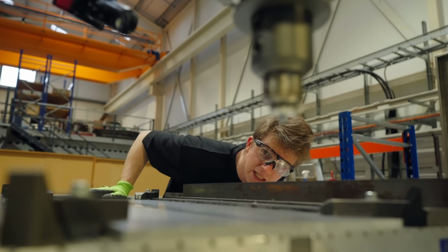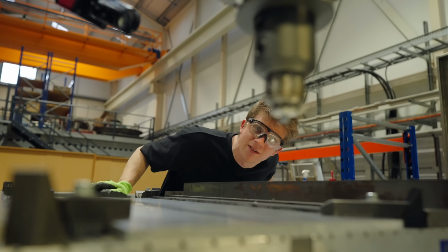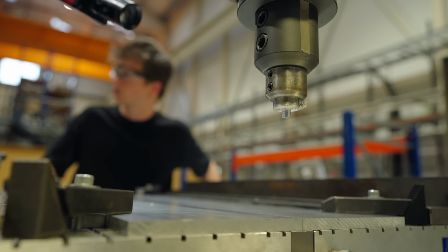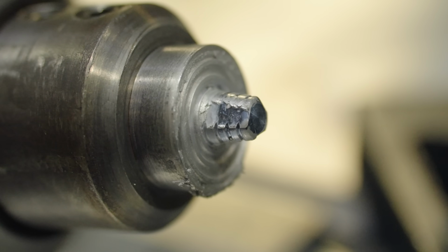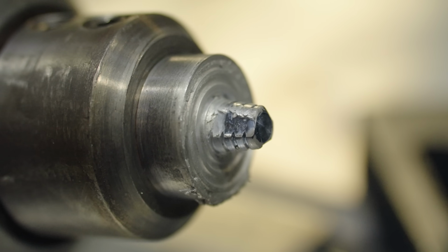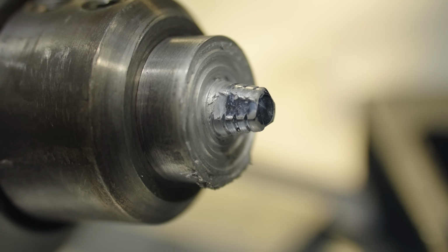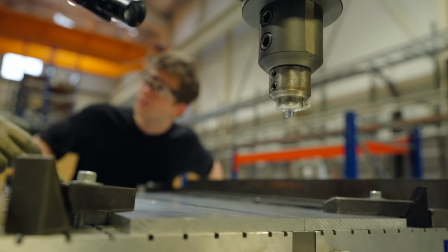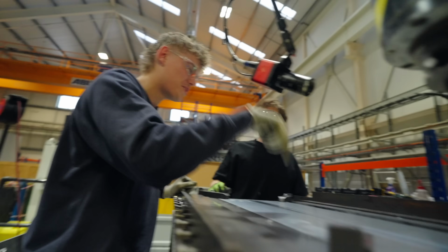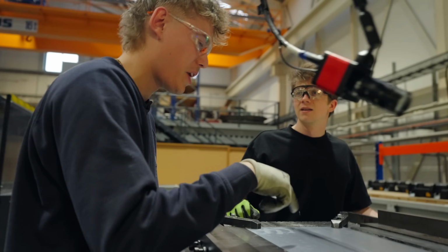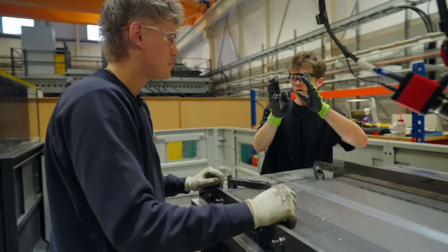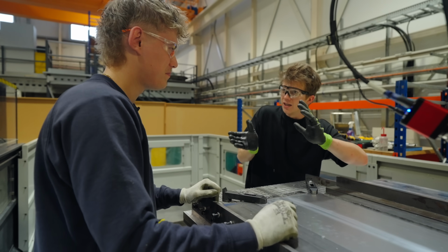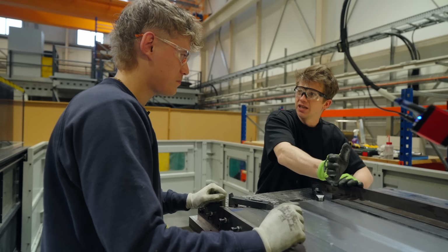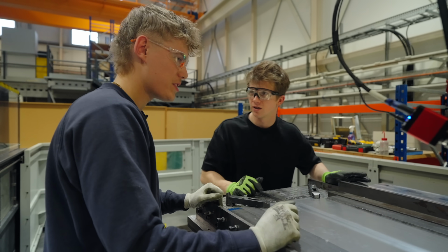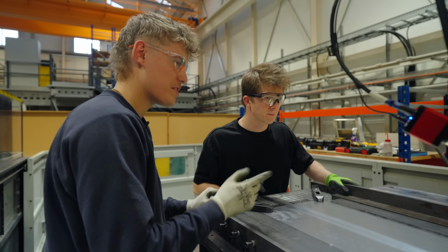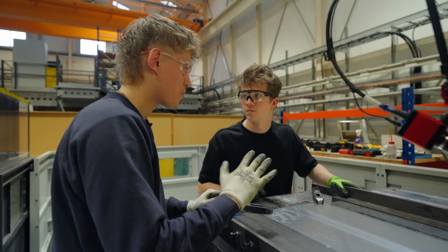So the friction stir welding tool for aluminium is different than for copper. That looks different than the one that we just saw on copper. Well, yeah, so we've got our tri-flat probe with 3 flats on, and then we've also got our scrolled shoulder, because we're welding at 0 degrees, whereas on the other machine we've got a tilt angle. Oh. So we're welding at 0 degrees straight down, and the scroll helps with the mixing of the material. So if you can't tilt the machine so the backside of it is forging that material, you have to have a different feature in the tool. We have a scrolled shoulder, yeah. Very cool. Whereas when we tilt, we have a concave or convex shoulder.